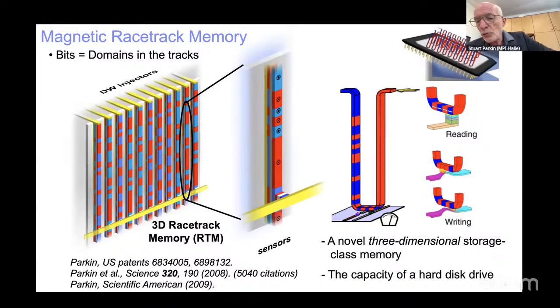circuits using conventional charge-based electronics, CMOS, in a silicon wafer, you build a vertical racetrack which could contain 100 domain walls, and then you move the domain walls, the stored information in the form of the presence or absence of a domain wall, by current pulses. You can move the domain walls, the memory elements, to reading and writing devices built into the racetrack. And in this way, in a small area of a silicon wafer, we could store 100 domain walls, increase the memory capacity by 100 times, and this would enable us to build in a solid-state memory chip a device with the capacity of a magnetic hard disk drive.